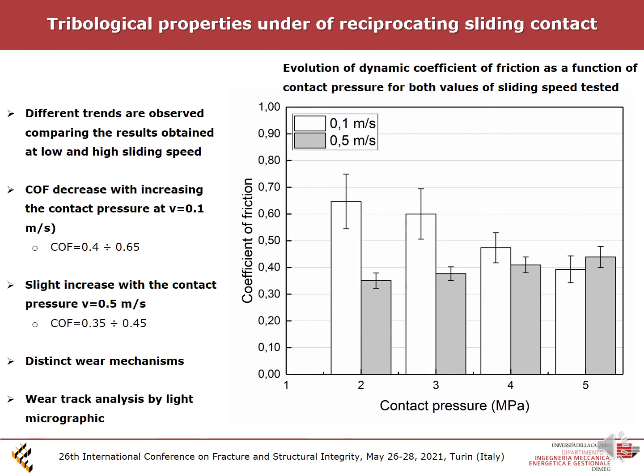The average values of the frictional data obtained through the entire sliding distance for the different values of contact pressure and speed analyzed show how the coefficient of friction tends to decrease with increasing the contact pressure for low sliding speed, that is 0.1 meter per second, varying in the range from 0.4 to 0.65, and on the contrary, a slight increase with the contact pressure is observed at higher speed, which is in the range of 0.35 to 0.45. These behaviors are attributed to distinct wear mechanisms, and to this aim,